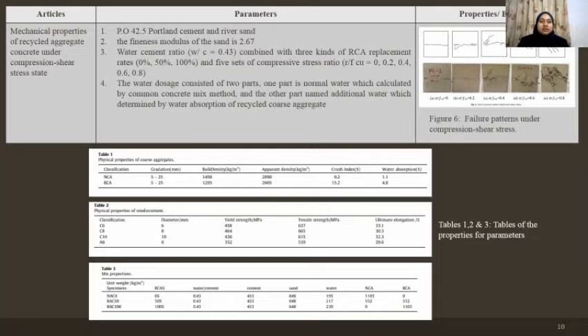In the last article, which is mechanical properties of recycled aggregate concrete under compression-shear stress state, the parameters used are Portland cement, which is 42.5, and river sand. The fineness modulus of the sand is 2.67, and the water-cement ratio is 0.43, combined with 3 kinds of RCA replacement rates, which are 0%, 50%, and 100%, and 5 sets of compressive stress ratio, which are 0, 0.2, 0.4, 0.6, and 0.8.